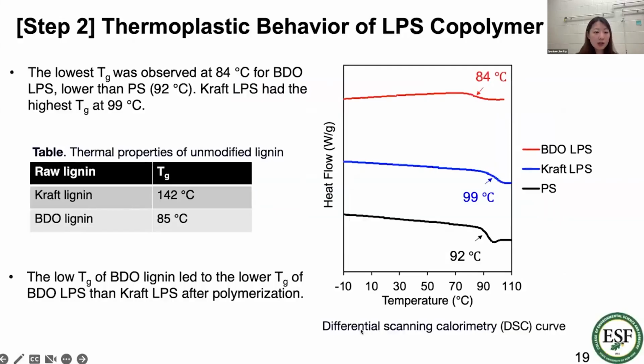We also measured the glass transition temperature of each polymer, because the glass transition temperature plays an important role when we process the polymer for commercialized material. The polystyrene showed 92 degrees Celsius, and Kraft LPS copolymer showed 99 degrees Celsius, which is a little bit higher than polystyrene. And interestingly, the BDO LPS showed 84 degrees Celsius, which was the lowest glass transition temperature among these three types of polymer. And we found these thermal properties derived from the original raw lignin thermal properties.